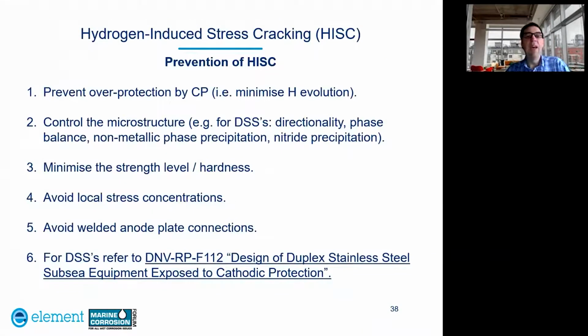So how do we prevent HISC? So first is to prevent overprotection by the CP system or minimize hydrogen evolution at the cathode. So the other way is to control the microstructure. So for duplex stainless steels, you need to look at the directionality, the phase balance, the non-metallic phase precipitation, and also limit the nitride phase precipitation.